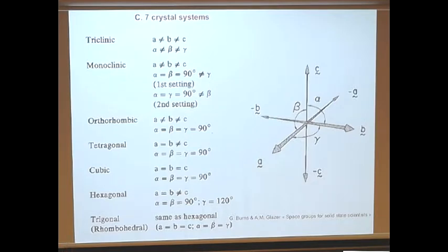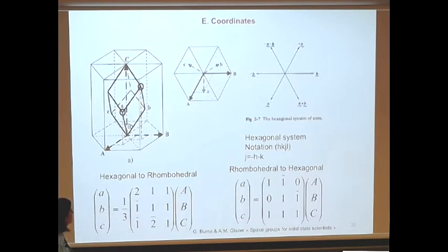But when you do real measurements, like X-ray diffraction, you need to be very careful because sometimes you are in error. To see if your a is equal to b or not, you may be within errors, because this difference might be very small. It depends how precise your measurements are, and sometimes you're not able to say from lattice parameters. I did my postdoc with a famous crystallographer, Professor Mike Glazer from Oxford. He repeated to us many times during one year: do not estimate the crystal system from lattice parameters. You cannot do this. You need to think about the symmetry and find what the symmetry is.